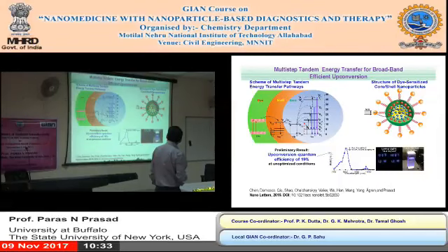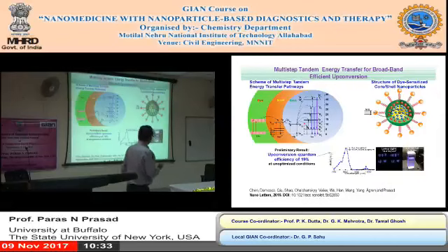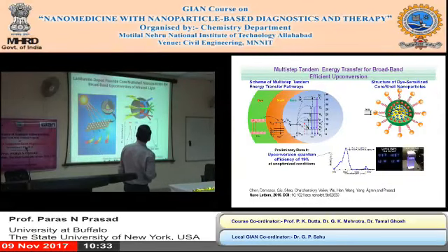Okay? Very strong, that you can even use a low power lamp. You don't even need a laser. A lamp at 980, in this case 800 nanometers, and it can be upconverted very strongly. Okay? So we showed that this energy transfer process, so these dyes act like antenna. They're antenna, they absorb light and they funnel the energy into the core where you can emit light. Okay? So then this is an example of core shell structure.